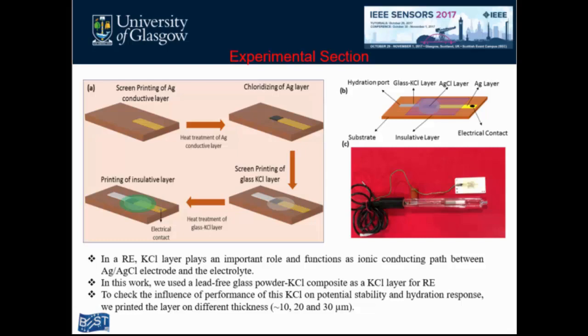Initially I used pure KCl and it easily dissolved in water, so my reference electrode had no long lifetime. The advantage of this paste is that it has a long lifetime, because, as you can see here, after that I deposited an insulative layer. A small portion is exposed through the insulative layer. This is called the hydration port.